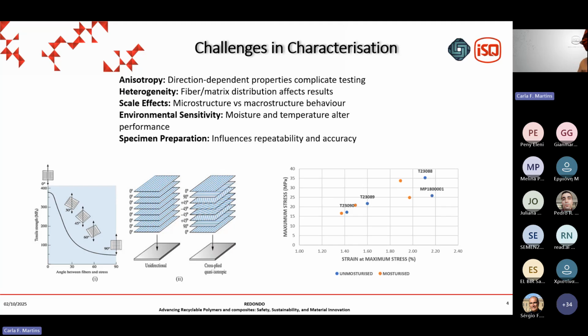And in there, we can have a very large variety of properties, as you can see there, where we have represented the variation of tensile strength of the material regarding the fiber orientation of that composite. They might have also other problems, besides this heterogeneity, like scale effects. So differences between microstructural behavior and macrostructural behavior resulting from the interaction between the matrix and the fibers.